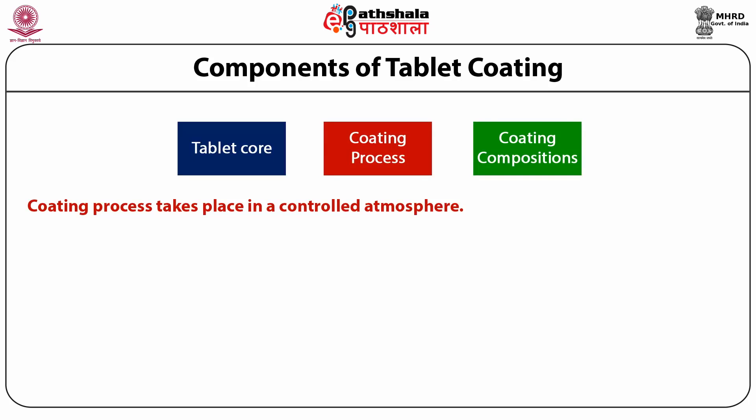The coating process takes place in a controlled atmosphere. Typically, the material to be coated — the tablet — is loaded inside a rotating drum called a coating pan. The geometry of the pan and angled baffles fitted into the pan provide means of mixing the tablet bed, lifting and turning tablets from the sides into the center of the coating pan, exposing each tablet surface to an even amount of coating formulation. Coating formulations are applied with the help of spray guns, which atomize the coating formulation to form small droplets.